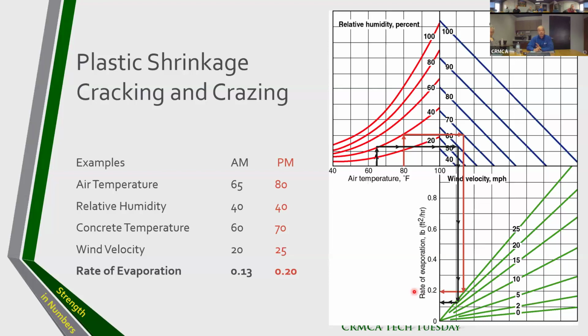So that means for an ordinary Portland cement, if it were a 1-2, in the morning you still would be okay. There's less risk of plastic shrinkage cracking, but in the afternoon there's for sure a higher risk of plastic shrinkage cracking and crazing. If it were a 1L, a 1T, I think I would already in both cases be careful and start fogging, curing beforehand to avoid plastic shrinkage cracking.